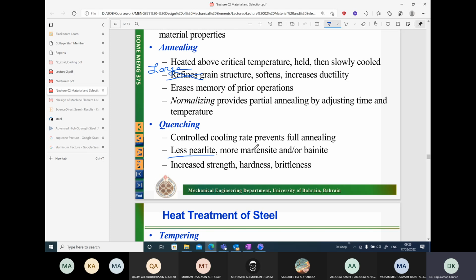You will have harder and harder materials formed. Why? The carbon in the steel does not have enough time to migrate from one grain structure to another, and most of the carbon will be caught in one place. When the concentration of carbon is high in one place within a grain structure, then martensitic structures or bainite structures will be formed, and these particular phases of steel have very high hardness. Pearlite, on the other hand, is soft, but less pearlite is formed in the case of quenching, especially steel, and it leads to hard steels. Okay, increases strength, hardness, but it becomes more brittle.